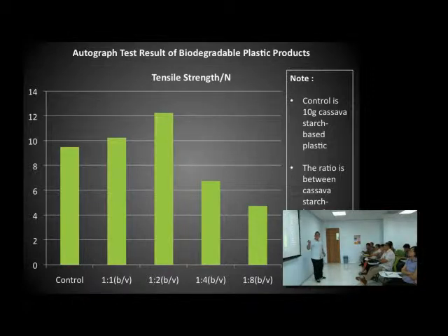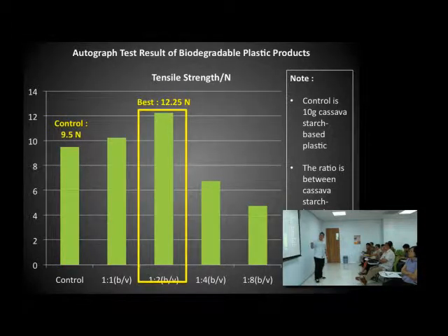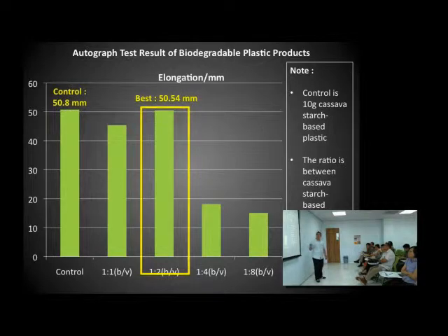Well, this is the autograph test result of the biodegradable plastic product in the original state. You can see that 1:2 provides the best result. It is 12.25 Newton, while the control is only 9.5 Newton. And for the elongation, 1:2 still provides the best result. It is 50.54 millimeters. But we can see that it doesn't have much difference from the control.